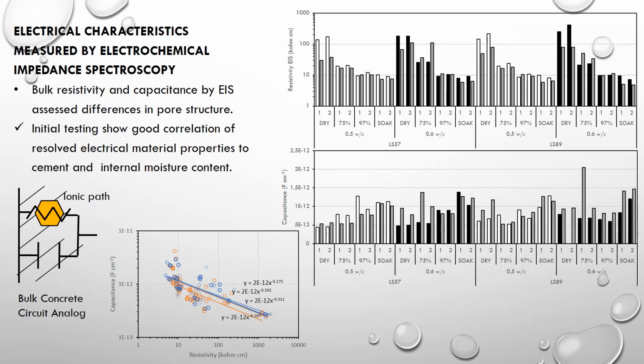And so since the concrete core samples were conditioned in those various moisture environments, we also tested different concrete parameters, including electrical parameters and acoustic testing. The idea for this type of testing is to try to gauge and correlate some of the measures we get from the water pressure drop onto some of these other parameters. And so we did some electrical testing, including electrochemical impedance spectroscopy.